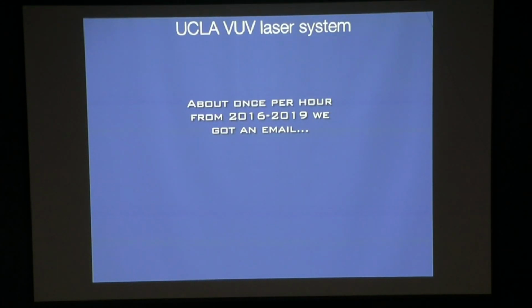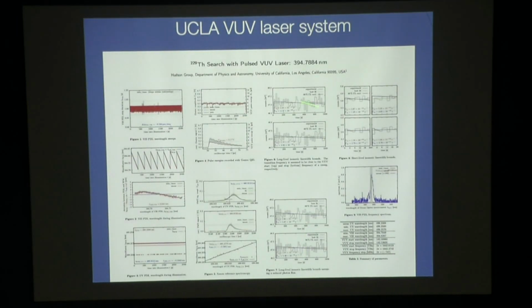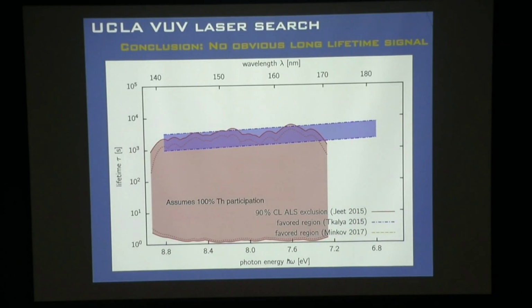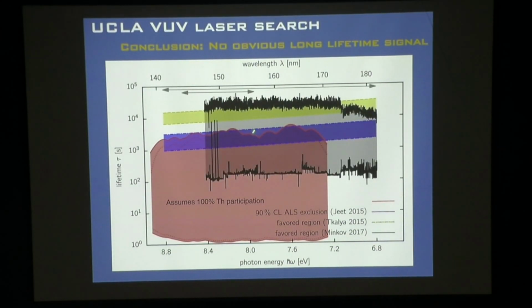All right. And so then about once an hour, because the lifetime is like 2,000 seconds, that's a good fraction of an hour. You get a data point an hour. We would get an email from the experiment, and it would look like this. You don't need to know what these are. They're just things about the wavelength, things about the power, things about the pulse spectrum. And then this is really the plot I mostly looked at. This is the number of photons in the first 1,000 seconds after we turn off the laser, and you hope to see exponential decay here, right? And so we did this scan for 3 to 4 years, and we saw nothing. And if you put this exclusion, we excluded at a really high level all the way down to about 147 nanometers.